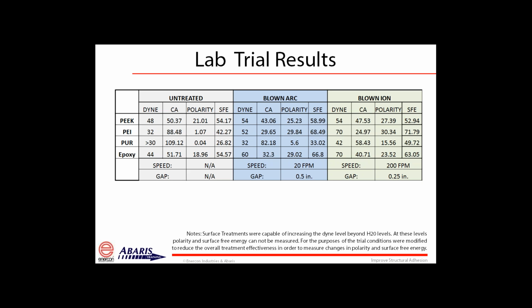Now, what was interesting as we went through and did these tests, we were trying to see how high a level we could get. When we measure dyne levels, the level 72 is what's known as water wet. We actually had to slow down the speed at which we processed these so we could get you some numbers that showed levels which were readable. When we had these running a bit faster, we were getting water wet, very low contact angles, very high surface free energy. So we can really affect the surface pretty significantly on any of these materials that we see.